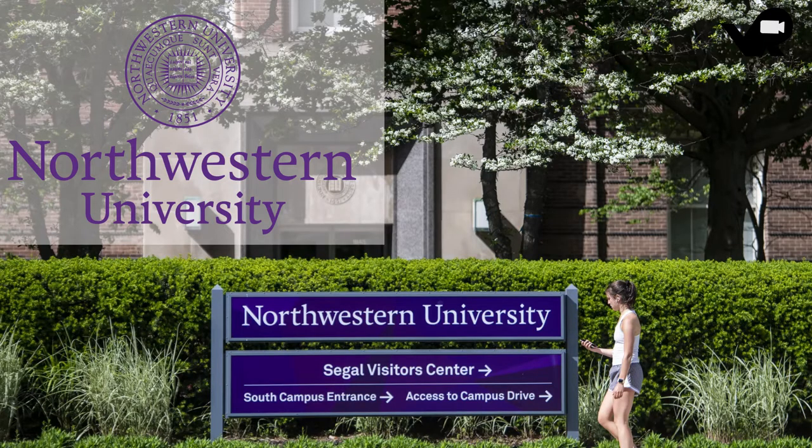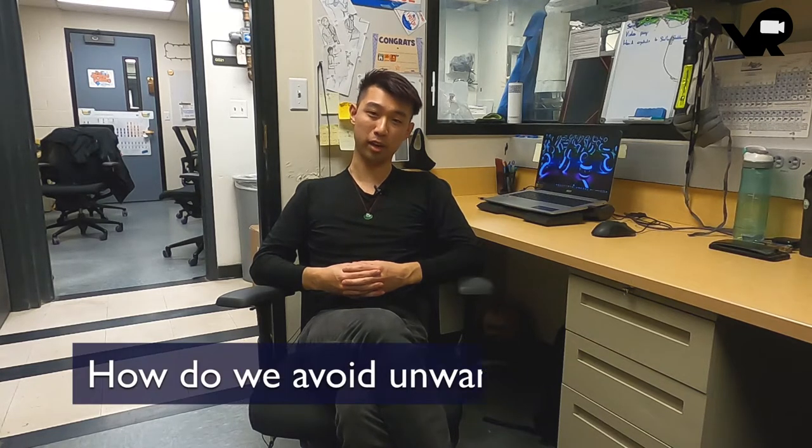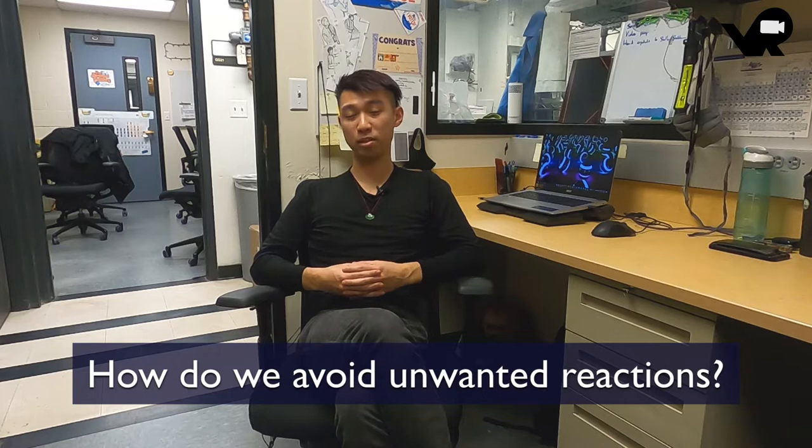And today, I'll be answering a question that we commonly get from our new students. For chalcogenide synthesis, how do we avoid unwanted reactions with atmospheric gases such as oxygen and water vapor? And the answer is that we carry out our reactions in fused silica ampules. And so today, I'll be showing you all how we do that.